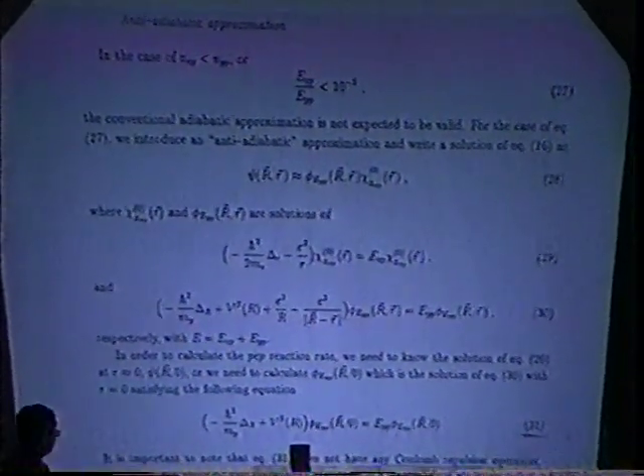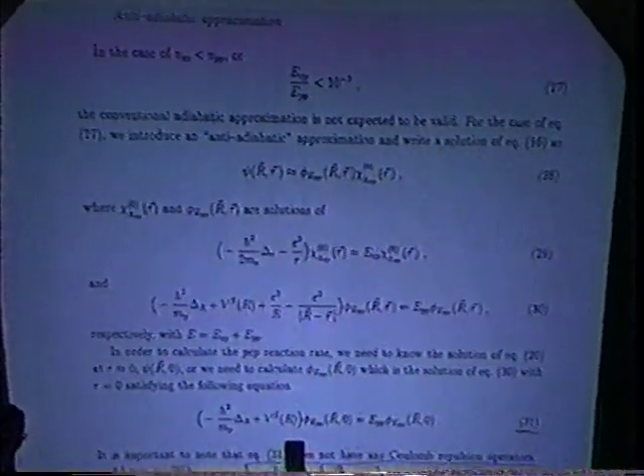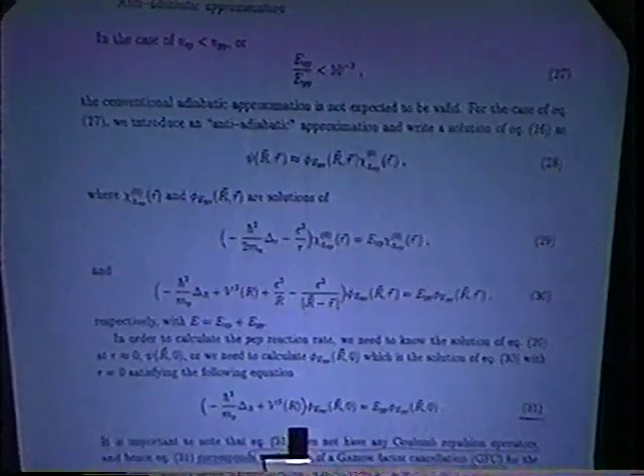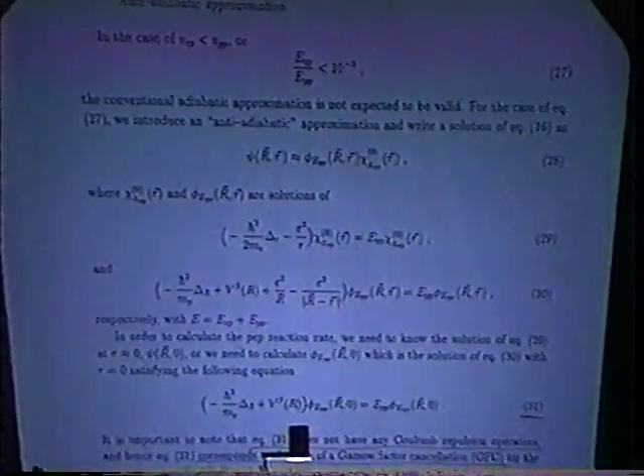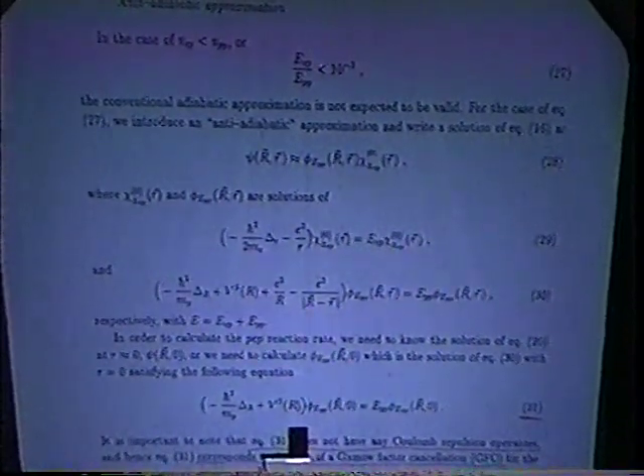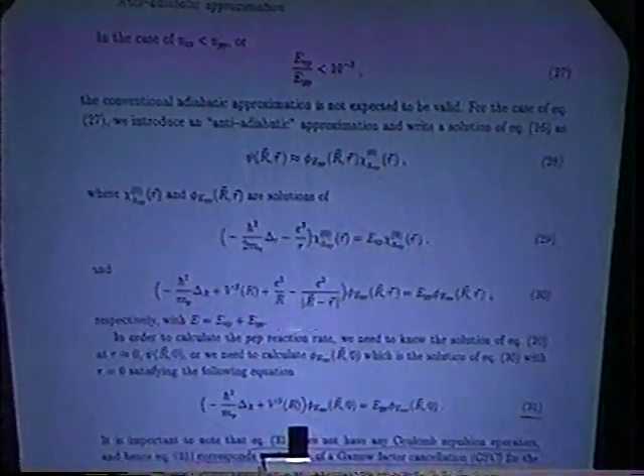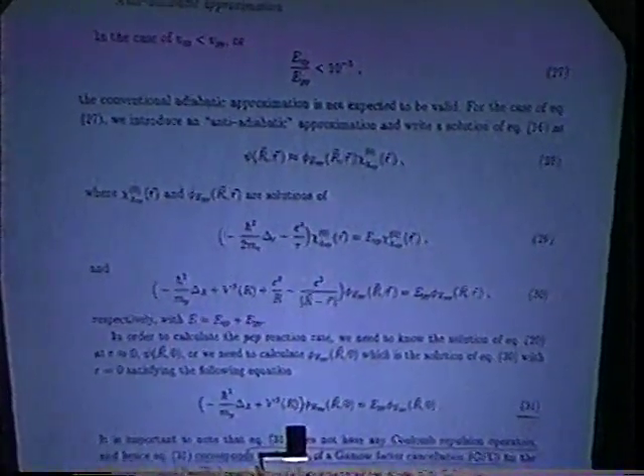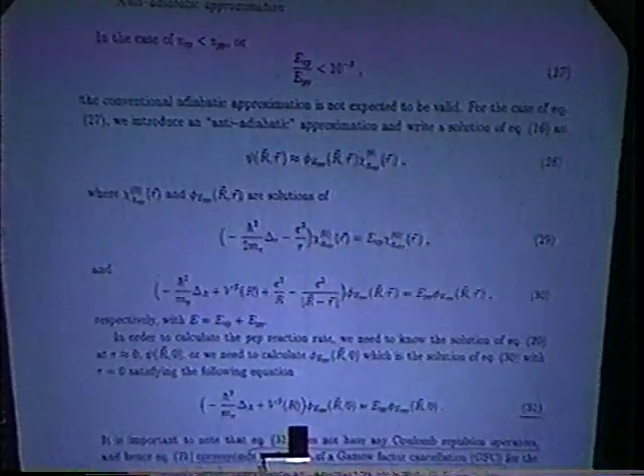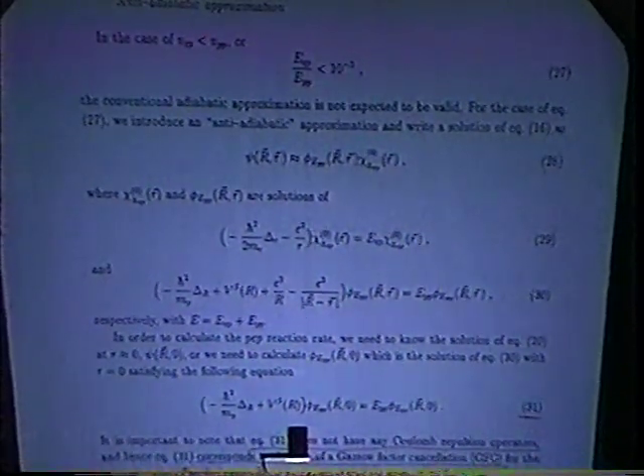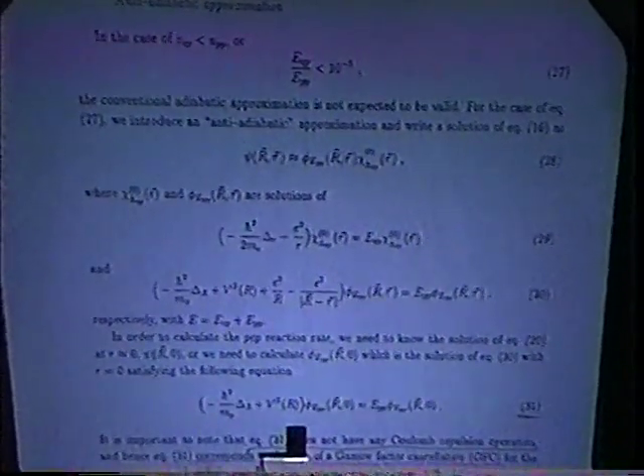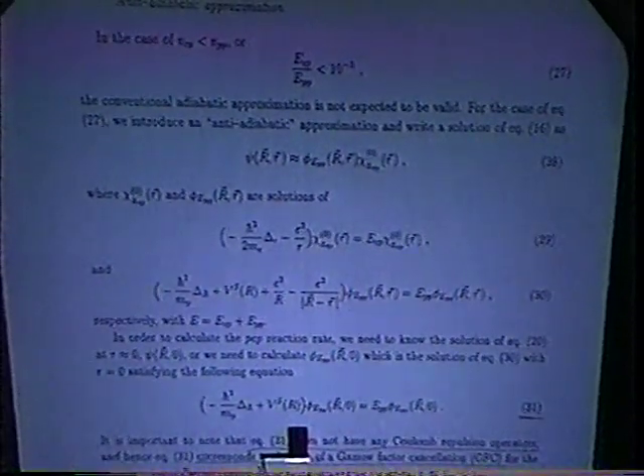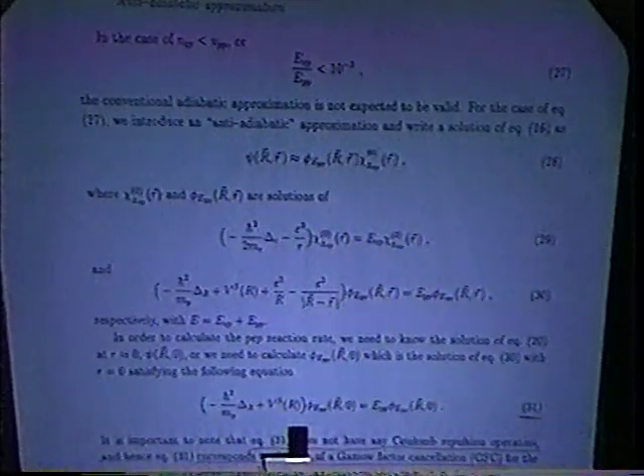And if the condition is right, then you can have a Gamow factor cancellation. And that condition is that the relative velocity between the electron and proton is much smaller than the proton-proton relative velocity. That translates to this kind of condition. If this condition is satisfied, you can write the equation solution in this form, and then separate the previous equation into those two forms. And if you want to know the behavior of the wave function between two protons, then you cancel those two terms and get this equation. So the Gamow factor cancellation can be achieved.